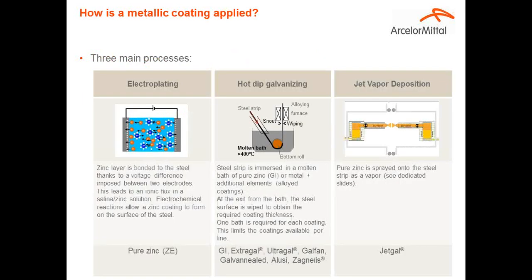So the coatings can be applied following 3 processes. The first one is electroplating. It is the oldest process to apply a coating. In this process, the zinc layer is bonded to steel thanks to a voltage difference imposed between 2 electrodes. And we have an ionic flux with a saline zinc solution in between the electrodes, and the electrochemical reactions allow the zinc coating to be formed on the surface of the steel. So that is how we apply what is called ZE, the pure zinc electroplated coating.